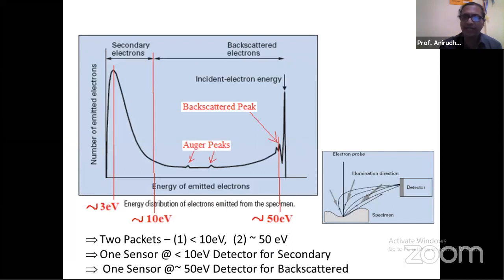Correct. Now, if you see these electrons which are emanating from this surface because of the effect of the incident electron beam onto the surface, if you collect those electrons which emerge out because of the incident electron beam, see in this case it is an incident electron beam, whereas in the case of XPS, which we discussed half an hour back, it was X-ray, but now it is a beam of incident electrons.